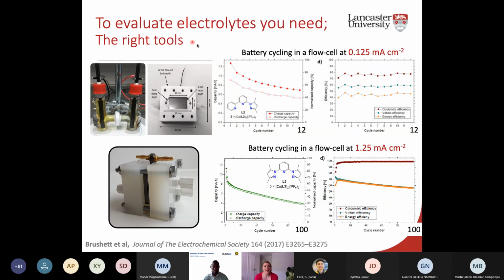So when we were looking at the mixed ligand systems, for example, we initially started with this really rubbish flow cell. We thought, well, a flow cell just needs a plate and a charging solution and chuck some electrons in, it'll be fine. But it's really, really hard. And we found we had really high resistances and lots of problems with the solution generally. And we could barely reach 12 cycles, and it took such a long time because our energy density, our charge density, was really low.